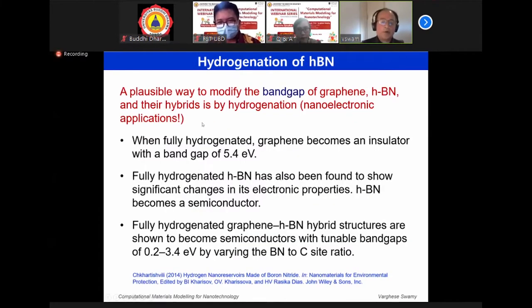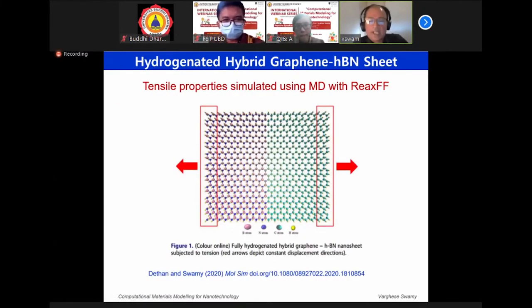Of course, I'm talking here about hybrid structures. That means two structures, HBN and graphene, in contact with each other contiguously without any grain boundary. And such materials are good for nanoelectronic applications. So what's shown here is Dr. Jacob Dethan's work for his PhD, and afterwards he did some work here where we have simulated tensile properties of such a hybrid structure. Here you can see the boron nitride to the left, and to the right is graphene, and these yellow balls you see on top are hydrogen.